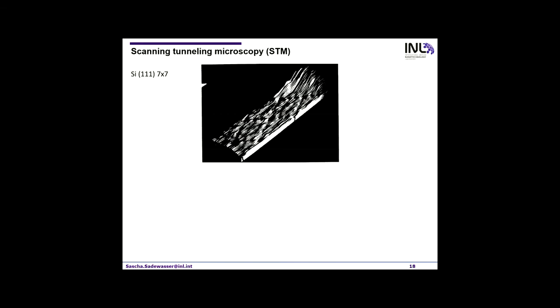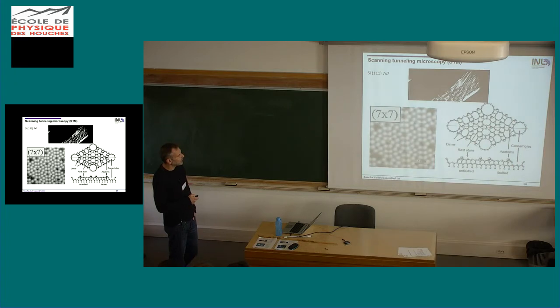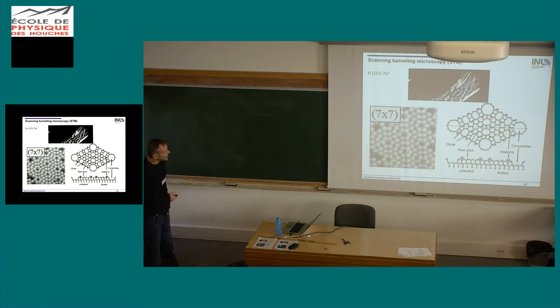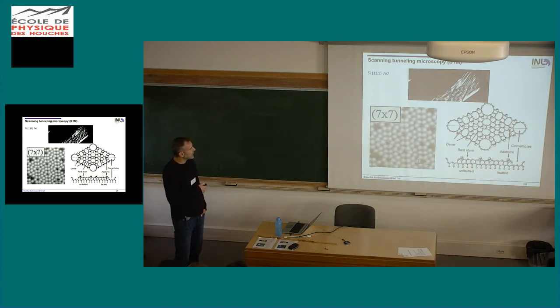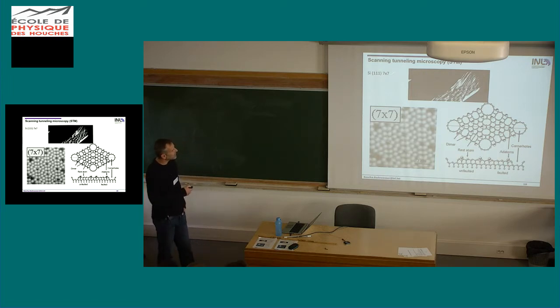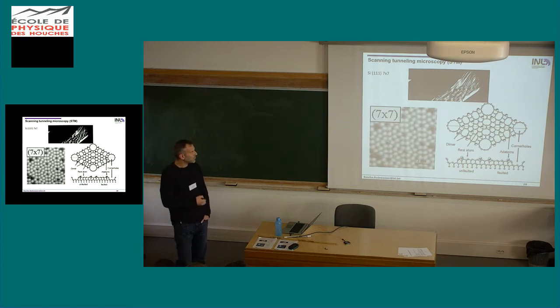So again, this image I mentioned already, this was quite difficult to measure. In modern times we have computers, so everything is computer controlled, and we get these images much nicer. And this actually was the image that helped to finally decide what the silicon 111 is. We just learned what the round brackets mean. It's a plane, and then there are different reconstructions of these surface planes. This one is a 7x7 reconstruction, which was known before, but it was not really decided yet how the structure looks. And this STM actually helped to identify how the structure looks.